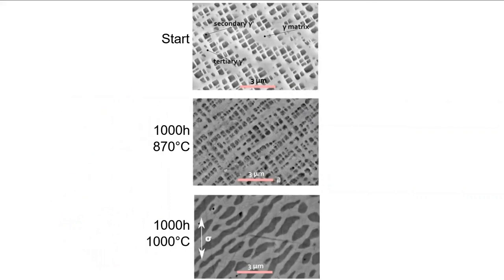These micrographs are from the same alloy, prior to and after creep testing. The microstructural features are not important, but the overall morphology of the microstructure is, on a qualitative basis. There's not much difference in how the microstructure appears between the starting material and even that exposed to 870 degrees Celsius for 1,000 hours. However, a difference by a few hundred degrees results in gross changes in the microstructure.